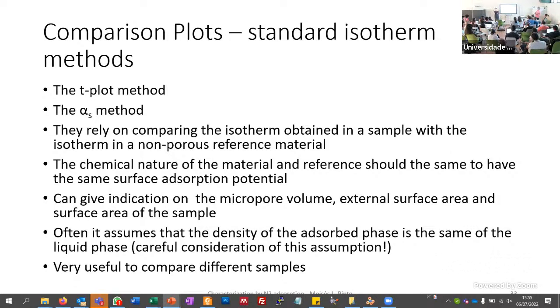So we assume that the nitrogen is condensing with the same density, which is something that you are really not sure about. Okay? So you need to be very careful with these assumptions. So it's very useful to compare different samples. This method is very useful for comparing samples.